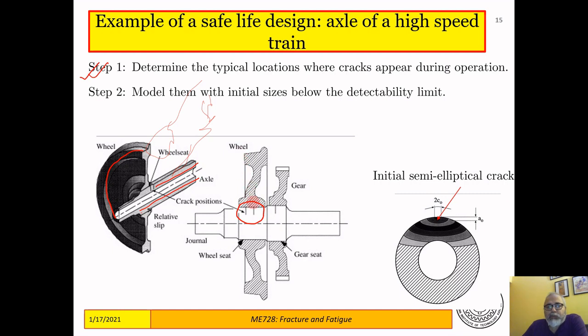So what you need to do is, starting from these likely places, you model the axle. This is the model of the hollow axle, and here I start with a small semi-elliptical crack. This is my starting crack, which has a major and minor axis of C naught and A naught. These are two quantities that are defined by my detectability limit. If my detectability limit is like 6 millimeters, like in ultrasonic testing, then A naught is 6 millimeters, and 2C naught is again given by the method by which I'm detecting the cracks.